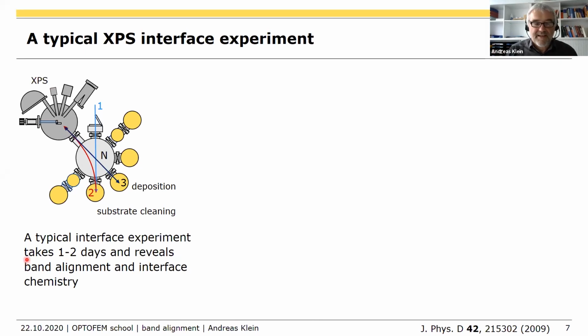One has to say that the deposition of the layer has to be very thin, because if you put 5 nanometers of your material on top, you don't see the substrate signals anymore. So what we usually do is deposit films with, let's say, 0.1, 0.2, 0.5 nanometers and so on. That can be easily done with our system. So that should not be a problem.